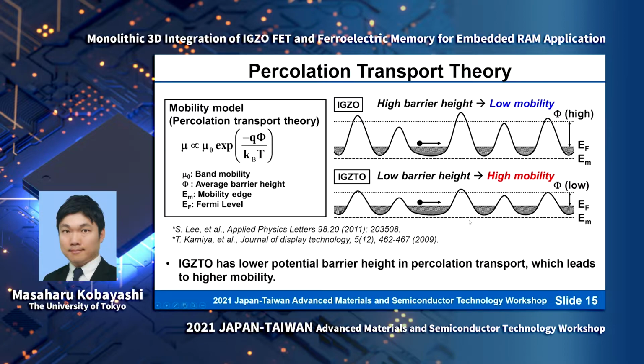If you have a high potential barrier, in other words high potential fluctuation in the amorphous material, you have a low mobility. But if you can somehow lower this barrier height, and have a smaller potential fluctuation, you can have a high mobility. So the IGZTO channel seems to have low potential fluctuation and low barrier height, so that it has a high mobility.